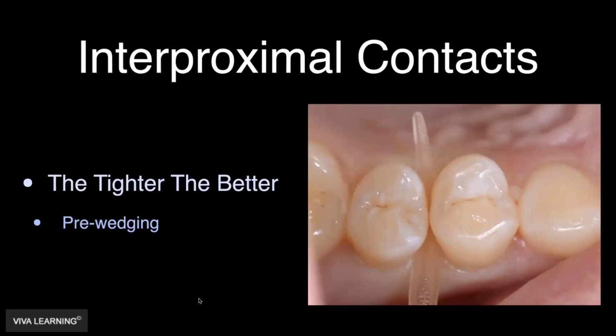Why does pre-wedging work? One of the two jobs of the wedge is to actually push the tooth, compress the periodontal ligament on the other side of the tooth, and separate the tooth enough of a distance to overcome the thickness of the matrix band. And the scientific research will show you that the wedge has to be in place 3 to 5 minutes to get really good separation. And putting it in after you've prepped isn't enough time before you actually start to place composite in a class 2 box.